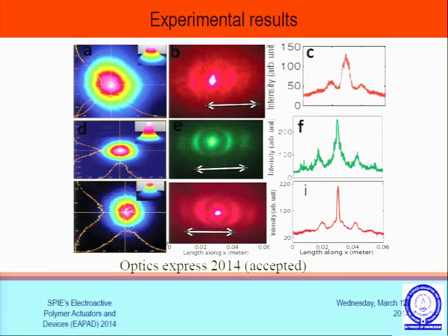If you can see the diffraction pattern on the screen, it means there is some regularity in the arrangement of the microstructure on the wing surface. But this regularity is not perfectly regular; the structure is not arranged in a proper regular way. Actually, disorder and order play a crucial role in building this sort of diffraction pattern on the screen.